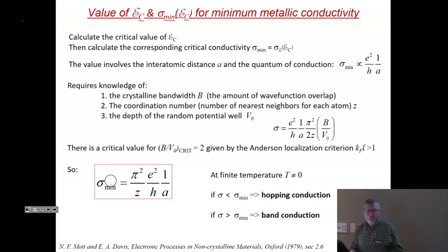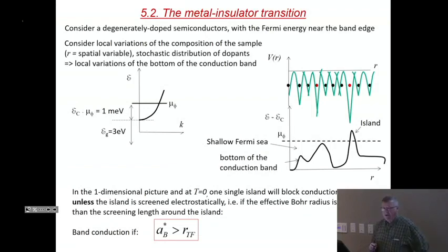If you are below that value, if your resistance is above that value, and typically for a sample it will be on the order of an ohm centimeter, then you can't apply the formulas that we derive for diffuse transport, such as the Hall coefficients and whatnot. It just doesn't apply. All right. Now let's look at the other criterion. The Mott criterion for the metal insulator transition.